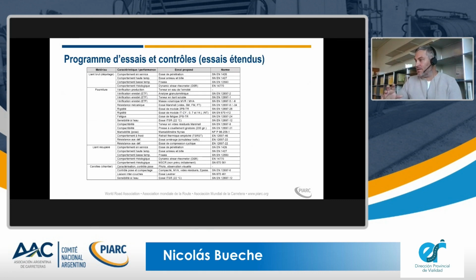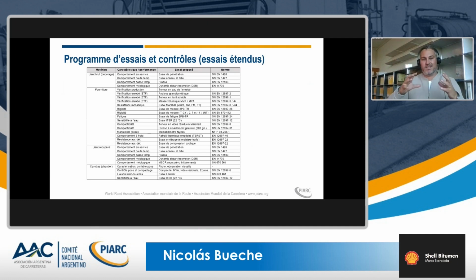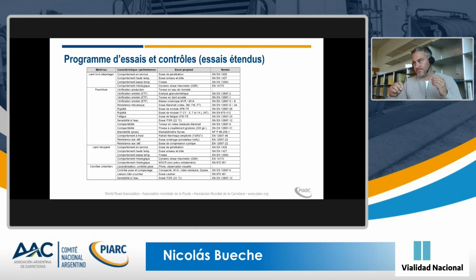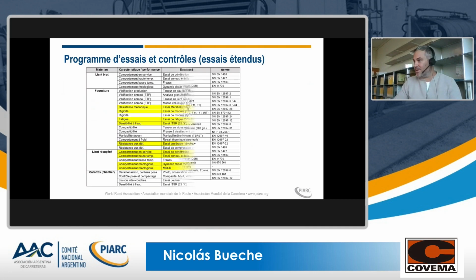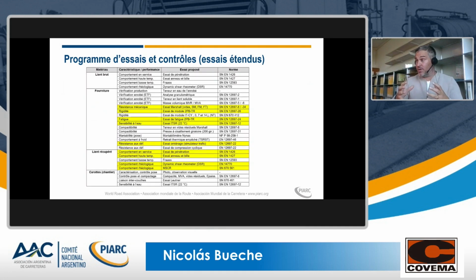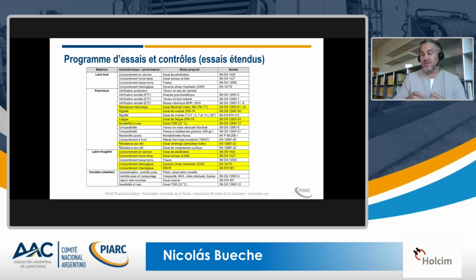This is just a general table to show you that we made quite an extensive laboratory testing phase. We analyzed bitumen, bitumen delivery, recovered bitumen, analysis of binder, analysis of the asphalt, low temperature and high temperature behavior, stiffness, rutting, etc. I won't speak about every test result, otherwise you will be a bit late for your lunch. We just pick some specific topics. Let's say, explain a bit what we got for the stiffness value, fatigue properties, rutting resistance, water sensitivity. Just a short summary. If you need some more information, please just ask. I will just briefly explain some results on the asphalt mixture scale and also on the binder scale.